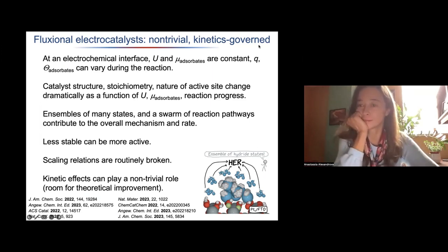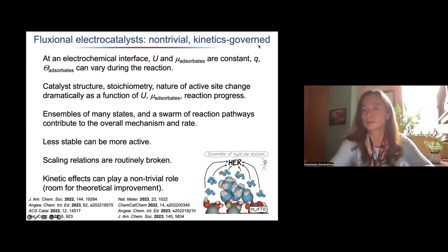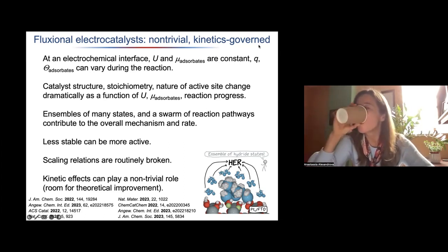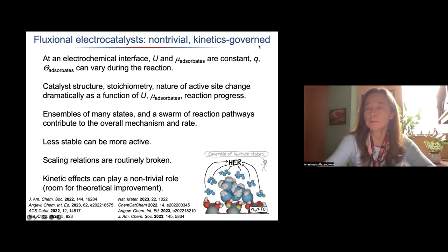That was very nice. Major points that Alexandra is making is that you need to do the calculations at constant potential, and as the potential changes, you get reconstruction, which can dramatically affect the results, but it's not necessarily full equilibrium, and entropy plays a role. Do you have any comments or questions from the audience? Just yell out.